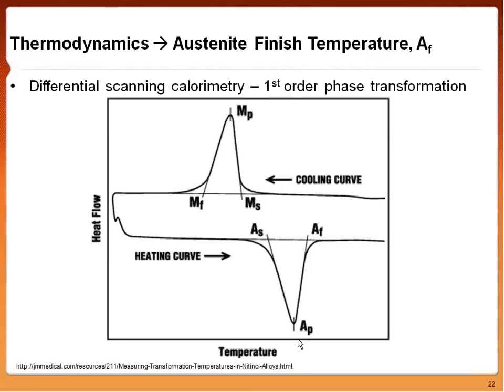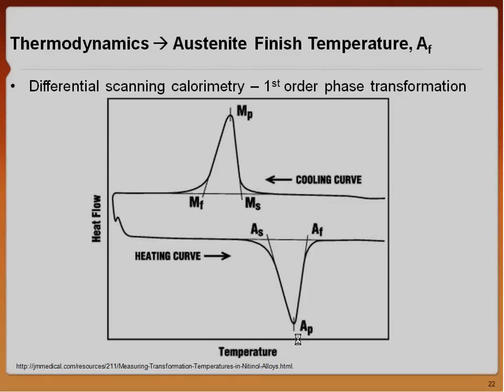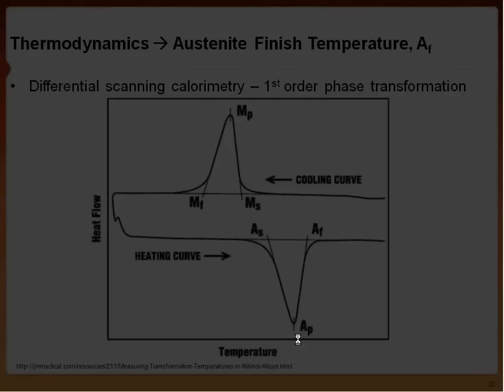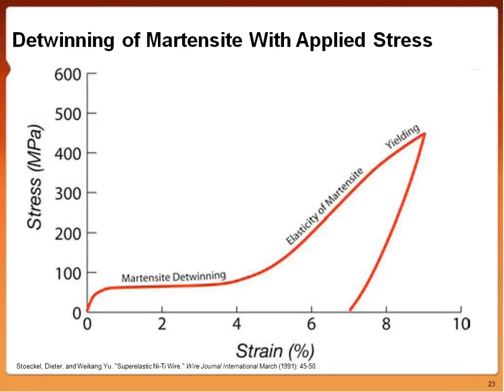So we understand Nitinol thermodynamics. We understand what happens with the Nitinol stress-strain curve when it's non-transforming austenite. And we understand how the martensite pockets nucleate within the austenite. So what then happens when we apply a stress to just a martensitic piece of nitinol? When we apply stress to a martensitic piece of nitinol, we see a phenomenon called detwinning of the martensite.